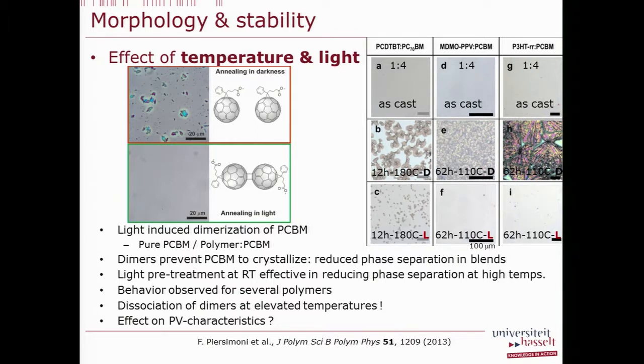We were not the only one seeing this. At the same time, also the group of James Durrant at Imperial College saw these effects. How can we interpret this? So the interpretation that has been given for this effect is that we have a kind of light-induced dimerization of PCBM. So the PCBM dimerize and become more fixed, and so the mobility goes down. So that's quite positive, this in relation to morphology and stability. So the dimers inhibit the PCBM to crystallize, reduce the phase separation.